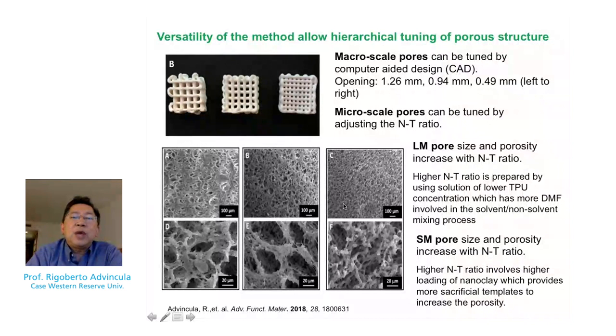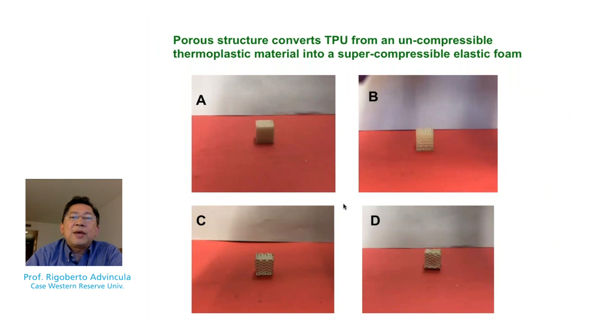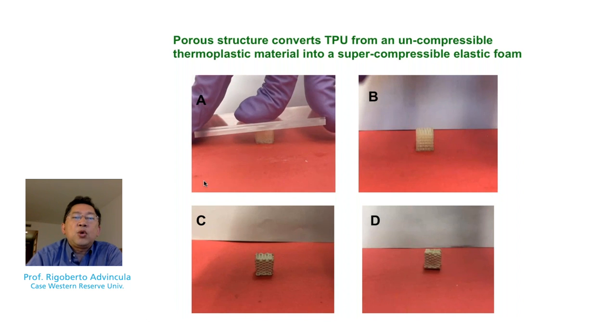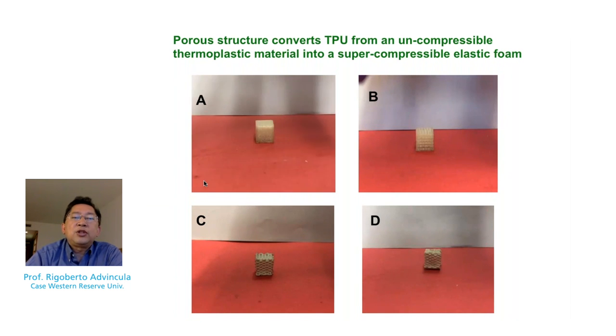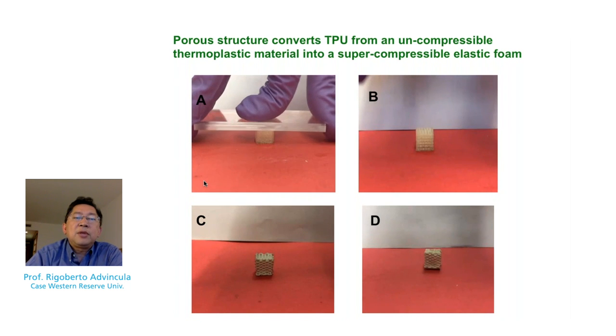So in this case, we actually made the object by 3D printing. We imbued the various thermomechanical properties. So what I mean is the 3D printing drives the opening size, but the procedure we use for making the foam allowed it to be more elastomeric. So in this movie, you'll see the 3D printed object as we prepared it, no conversion to the elastomer, simply based on the geometry and the opening size.